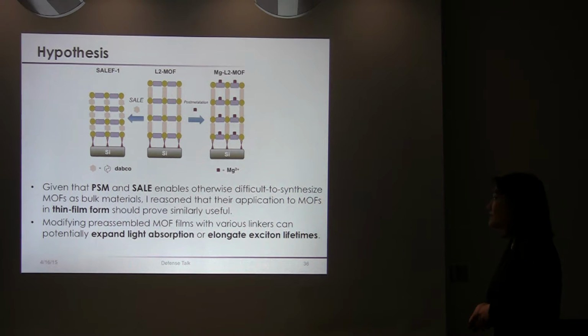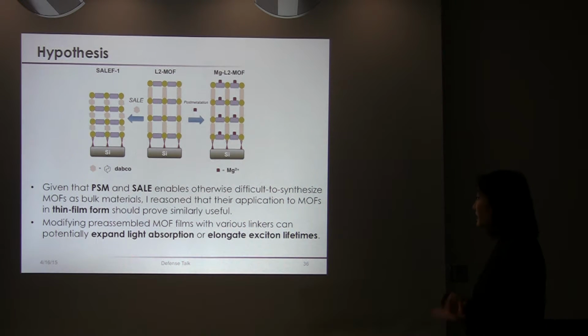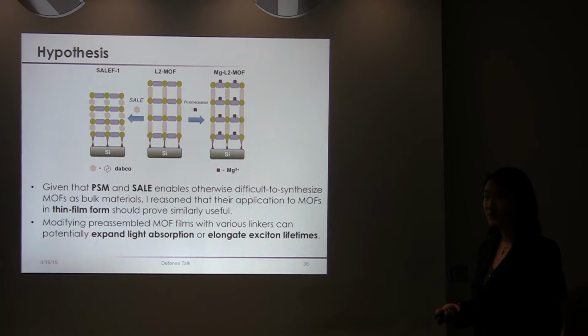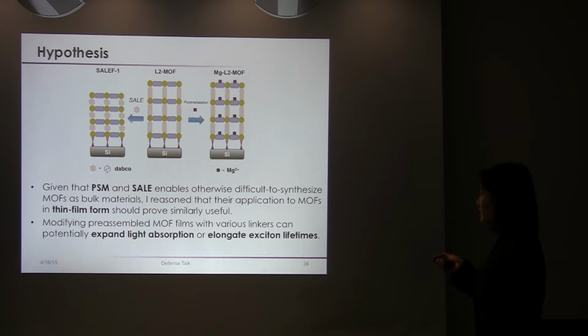So my hypothesis for this work was that given that PSM and SALE both enable the formation of difficult to synthesize MOFs as bulk materials, I reasoned that if I applied this technique to thin films, then I should also get similar results. What I've shown here is that by using SALE, I would form the SALEF1 film from this parent L2 MOF film, and by doing post-metallation, I can form this magnesiated L2 MOF film. Bringing this back to the original challenges, by modifying pre-assembled MOF films with various linkers, I can potentially expand light absorption or even elongate exciton lifetimes if we want to use these techniques to modify MOF films in the future.